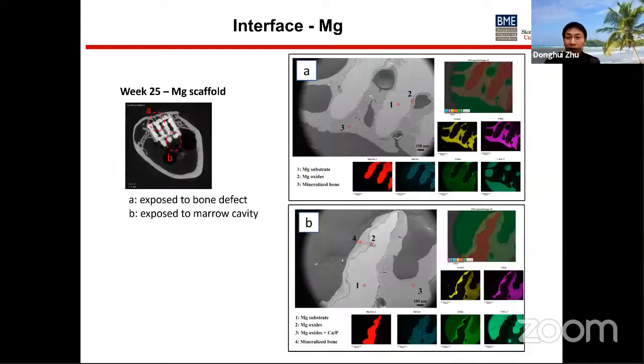This is 25 weeks after implantation. There is still some thin oxide layer covered by mature bone at the defect region A, while a great portion of the scaffold is already converted to oxide and calcium phosphate compound in the cavity, or B region.